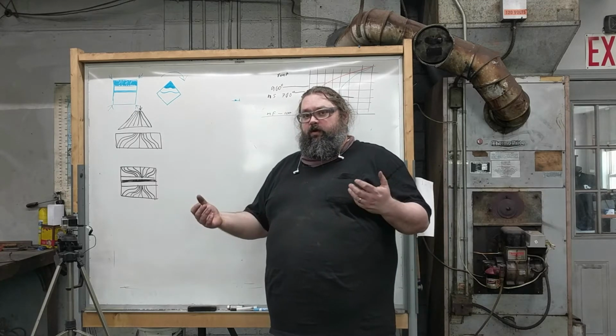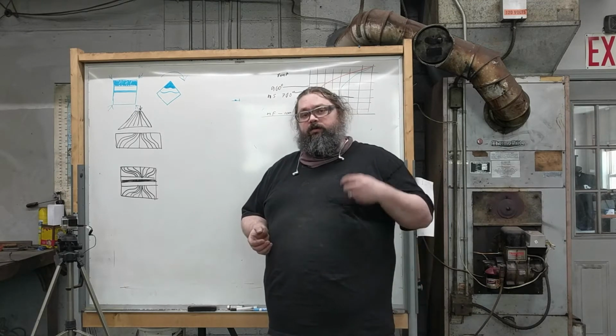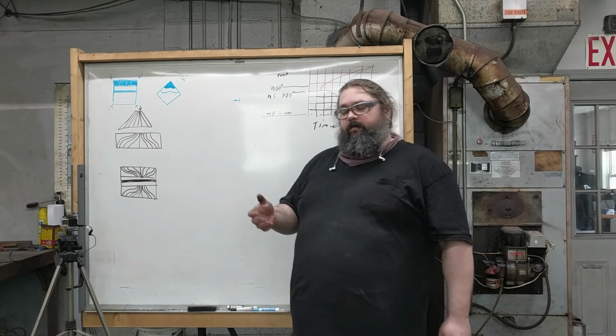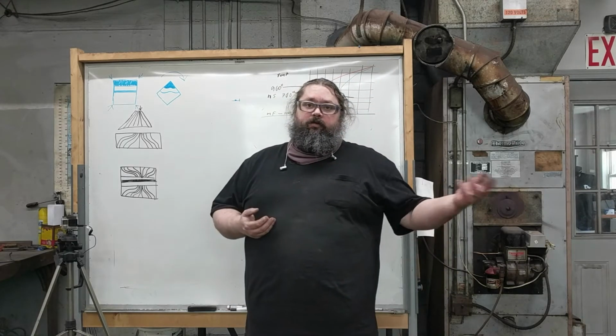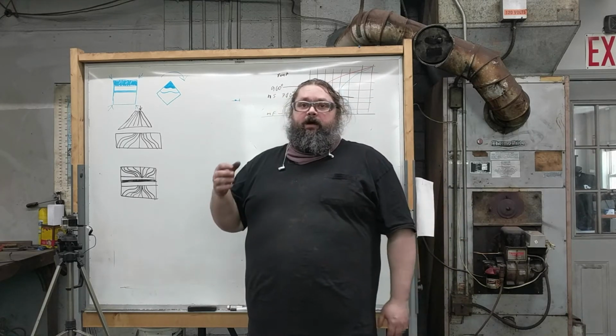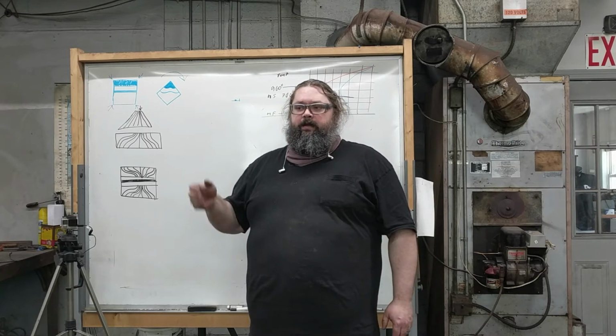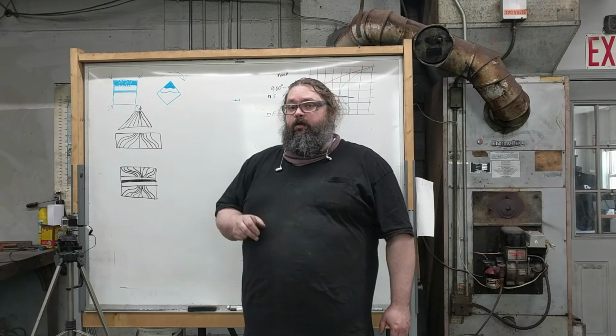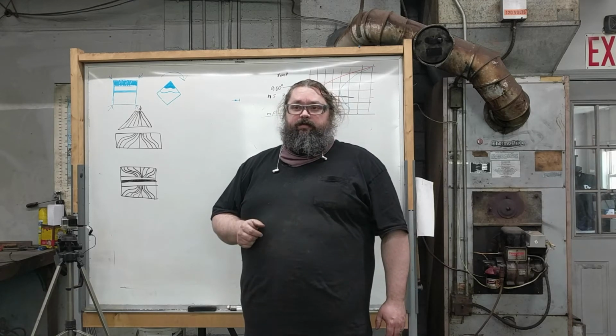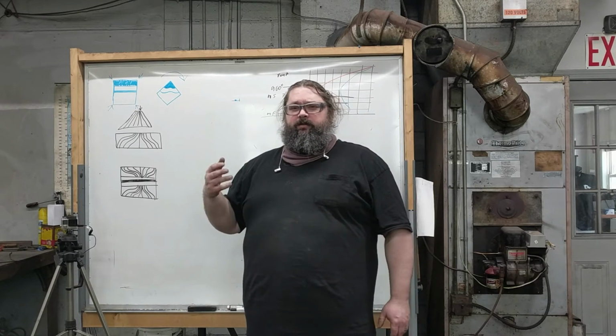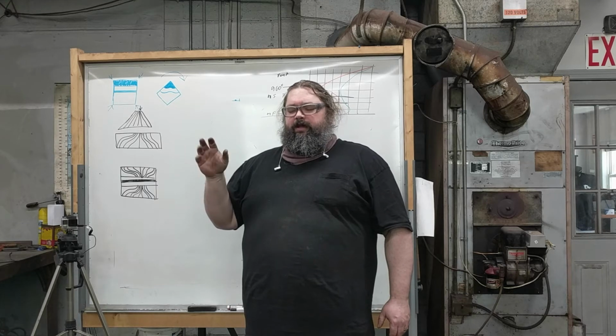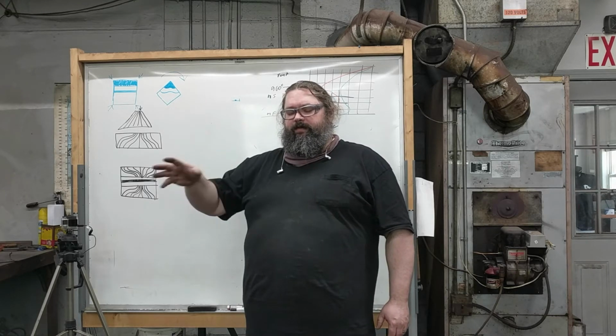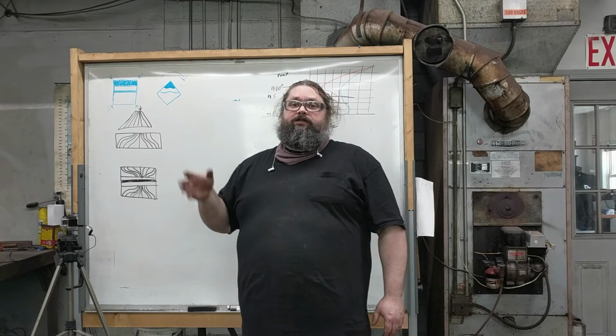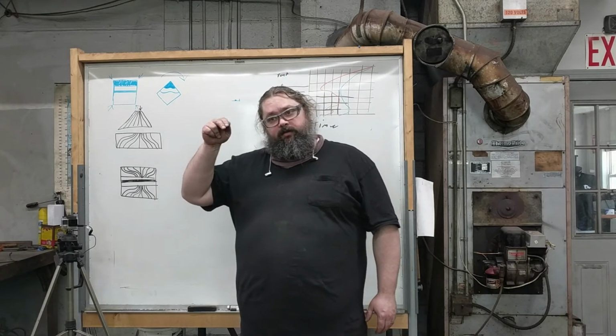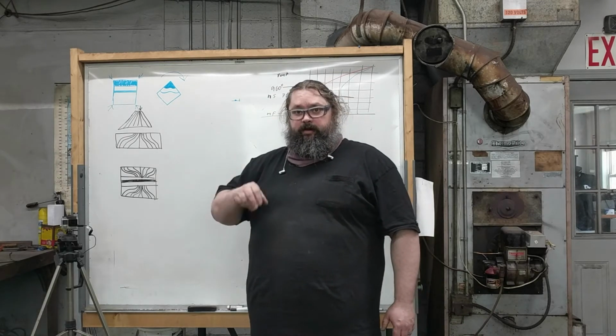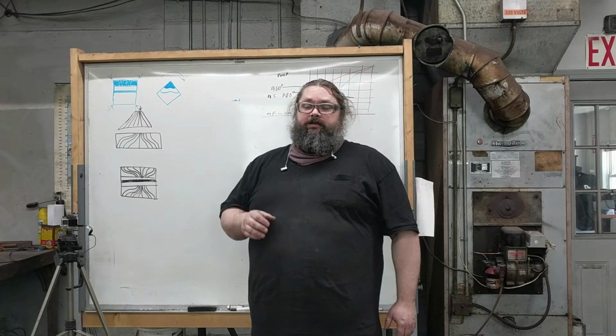The 2 points we really worry about is if it's below 100 or below 200. 100, if it's 100 degrees below zero, you can use dry ice or a little less, and that'll get you to like 110. If it is below that point, as it is with like ATS 34, S30V, some of the others, those steels need nitrogen, and nitrogen gets down below 250 degrees below zero, and that will convert that austenite.